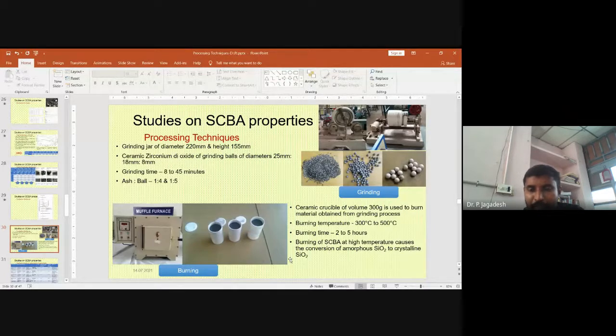Grinding time is varied between 8 to 45 minutes to get a minimum size of particle and appropriate particle size distribution. The ball to ash ratio is kept as 1:4 and 1:5.